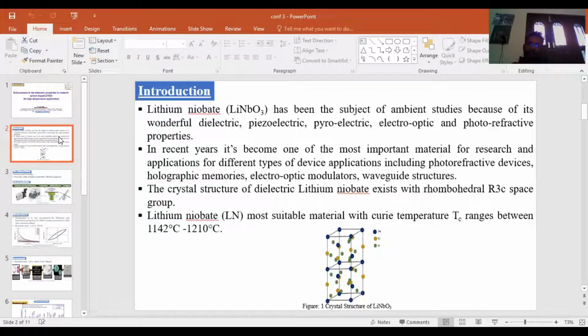The crystal structure of lithium niobate exists with the rhombohedral R3C space group, and the Curie temperature of lithium niobate is very high. The Curie temperatures reported by many scholars and researchers range between 1142 degrees Celsius and 1210 degrees Celsius. I have also shown the crystal structure of lithium niobate, where the different atoms are presented by different colors, in figure 1.